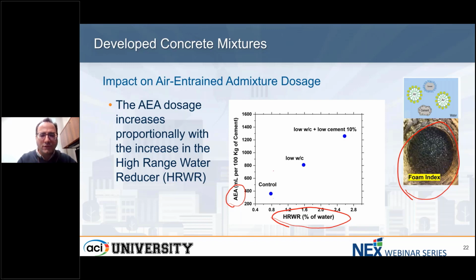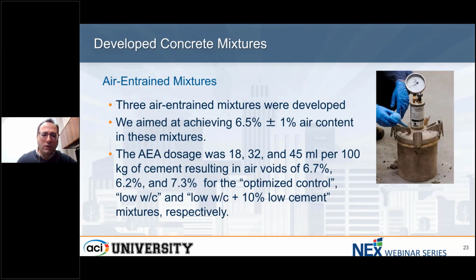As you can see, when we move from the control system to the sustainable low cement 10% one, we are moving from 400 milliliters per 100 kilograms of cement to almost 1400. So that's the proportion of increase in air entraining admixture we are expecting. We used this preliminary data to design our air entraining mixture. The target was 6.5% air content. We required 18 milliliters per 100 kilograms of the air entraining admixture to get to that point for the control one. While for the optimized one with low water cement ratio and 10% low cement, we required 45 milliliters per 100 kilograms. That's almost 2.5 times more air entraining admixture to get to that target air content.